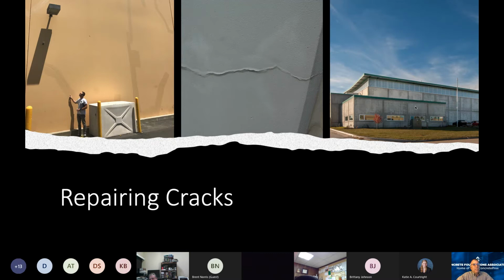In this particular case, the temperature of that steel, as this was built during the summer, had excessive heat in that face of the panel and caused cracking to map over the top of the steel reinforcement because of the curing, the rapid dimensional change of the concrete, much like the crazing cracking that I showed you earlier, only happening on the downside surface of a tilt-up panel. So a pretty difficult crack to control, but it's one that's based on the temperature of the steel at time of concrete placement.